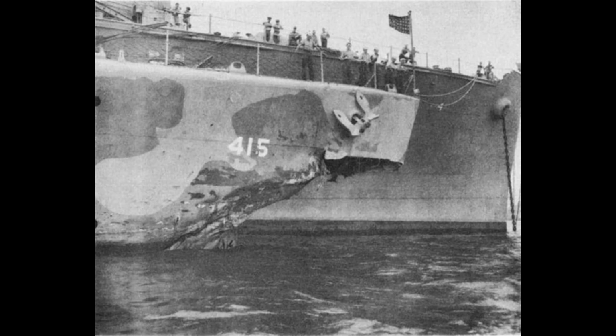Tipper demonstrated this phenomenon with elegant simplicity. She tested identical steel samples at different temperatures. At room temperature, the samples bent and deformed when struck. At cold temperatures, they shattered like glass. The difference was not in the steel's chemical composition or the quality of its manufacture. The difference was purely temperature.